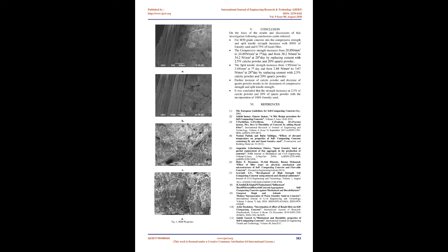Compressive strength. When the cement is replaced with 2.5% calcite powder along with 15% quartz powder, there is an increase in compressive strength. Further replacement of cement with 2.5% calcite powder along with the addition of 20% quartz powder gives maximum compressive strength. When the cement is replaced with 5% calcite powder and 10% quartz powder, there is a decrease in compressive strength. When the cement is again replaced with 10% calcite powder and 10% quartz powder, it results in a decrement of compressive strength.